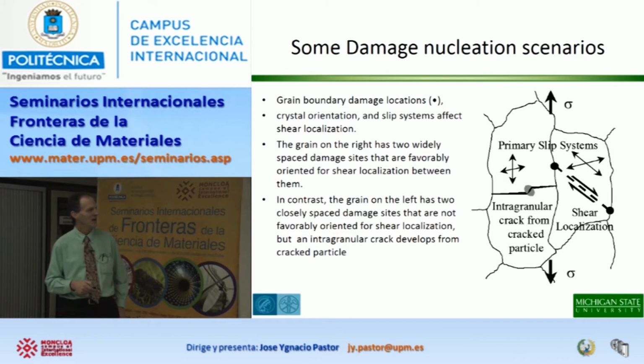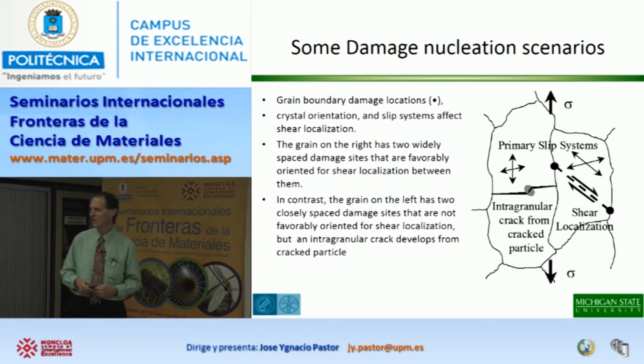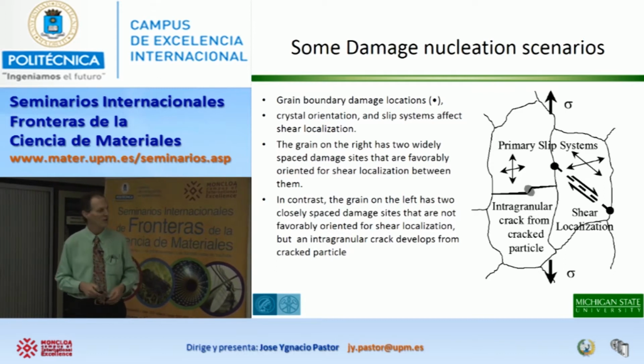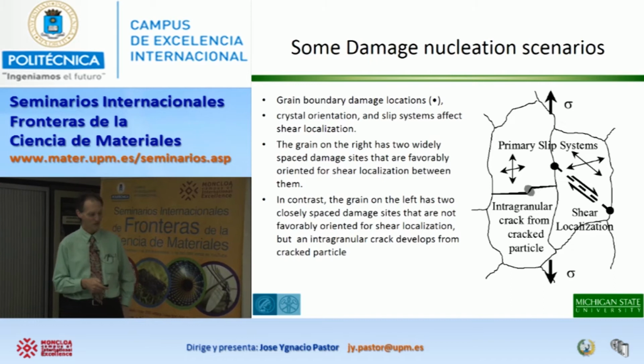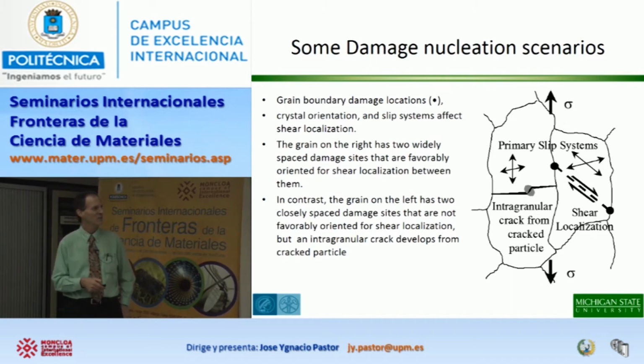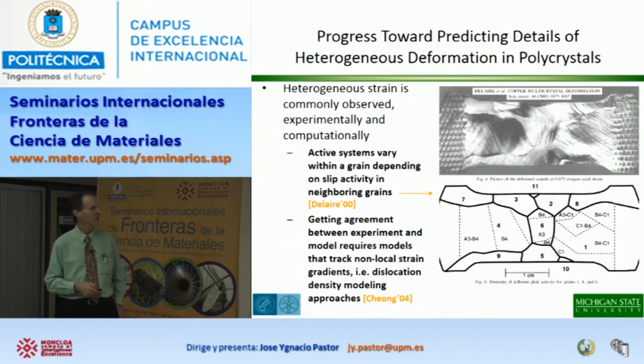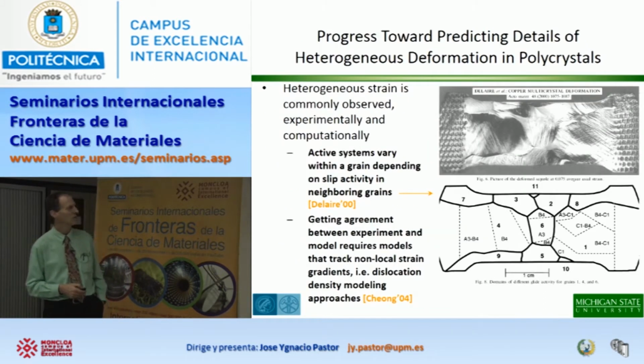On the other hand, if I had maybe even a damaged particle inside that may nucleate a crack, this particular site may not even interact with this one, even if it's closer, according to the nature of the slip systems that are involved. So this is partly the point that I want to make, is that slip systems are pretty important, and understanding what's happening locally needs to be worked out.